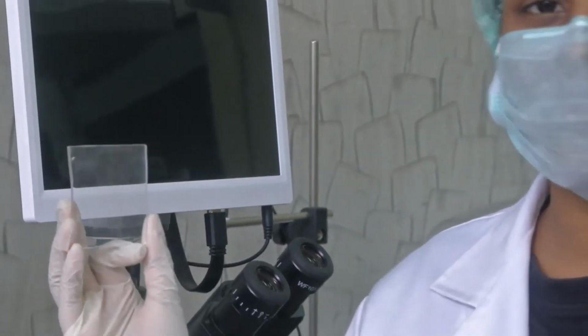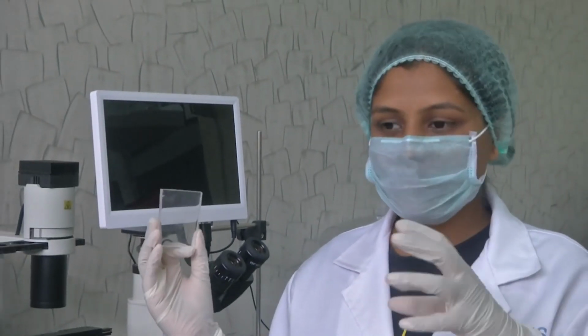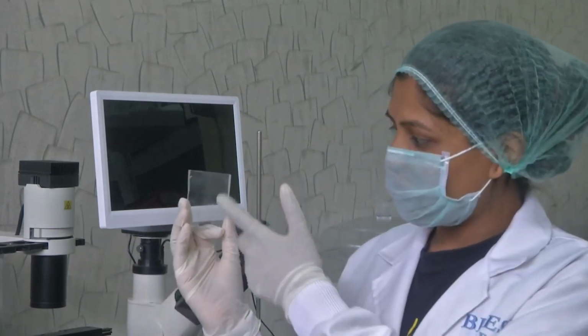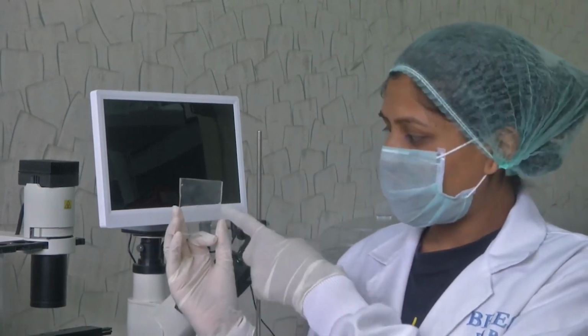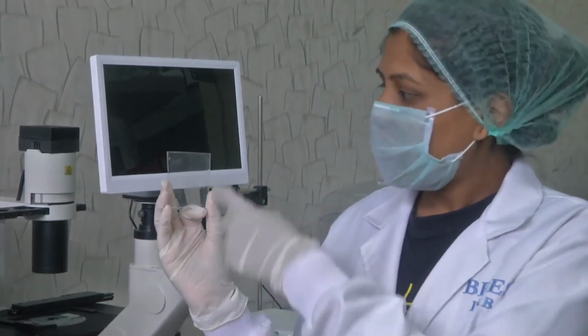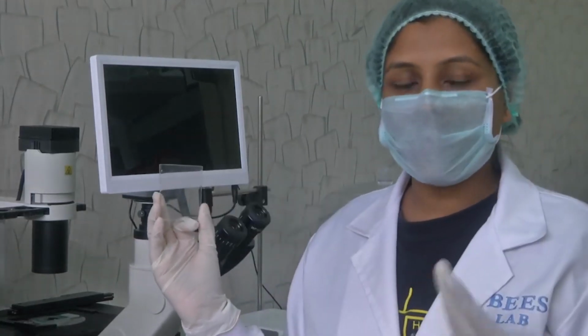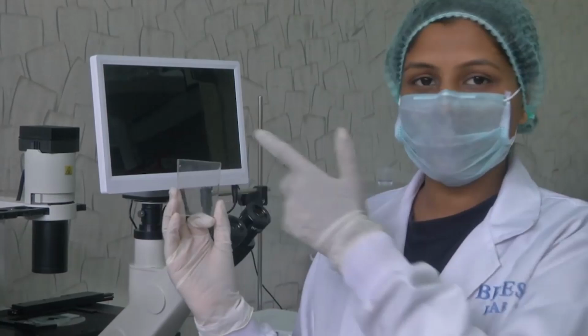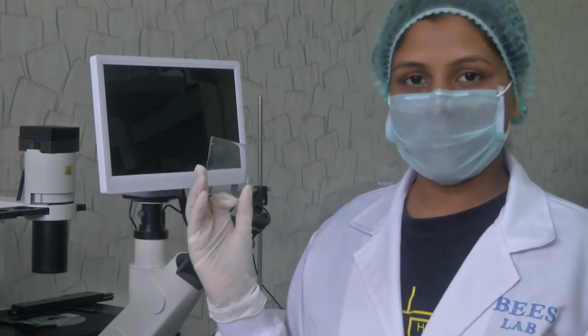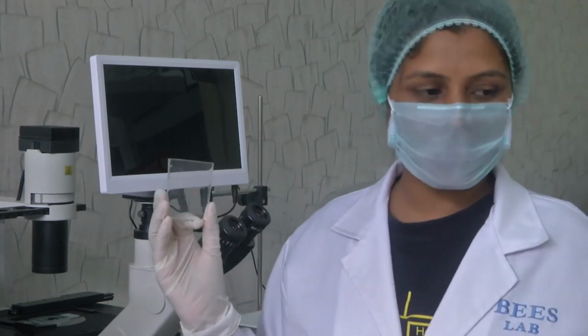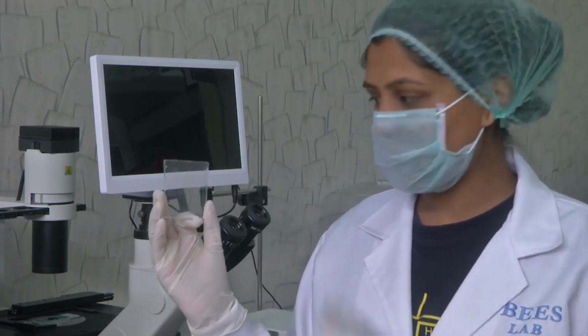Ideally, we are trying to make devices with micro channels and then flow fluid at some rate, so that we are able to get droplet formation or we are able to send bacteria and then see its susceptibility. For all of these tests, mostly they are liquid based, and when they are flown through these channels, bubbles could create some sort of blockage. That is why you always have to make sure that you do not have any bubbles while you do the entire process, from being mixed to being cured. The degassing becomes an important process.